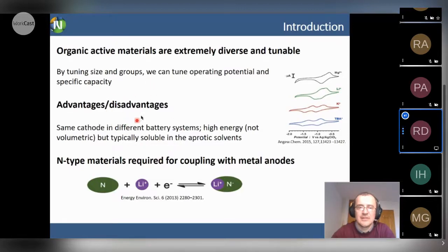But there are some disadvantages. The major disadvantage is that they need to be polymerized, or they need to be grafted to some non-soluble substrate, which is not soluble in aprotic solvents that are typically used in this new type of batteries. And what I would like to stress also is that it is highly recommended to use only N-type materials, since P-types need a large excess of electrolyte, which then decreases energy density, and such battery types usually don't have a really commercial or practical value.